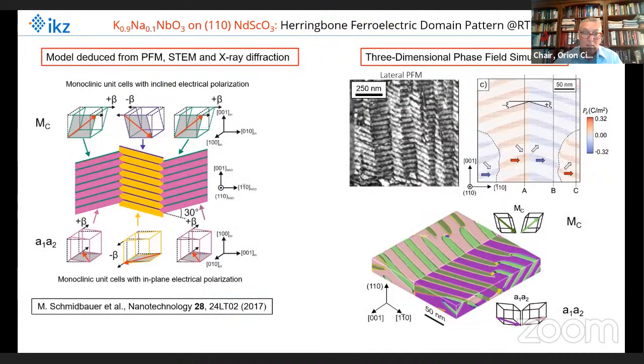Okay, so at this slide, I will first start at room temperature. You see here at the left side experimental proof of this mixture. We indeed find a model where we have a coexistence of MC monoclinic phases and A1 monoclinic phase. So the MC phase is shown on the left side top. You see the unit cell where we have this shearing, and the polarization vector lies within this plane of the unit cell and is inclined.